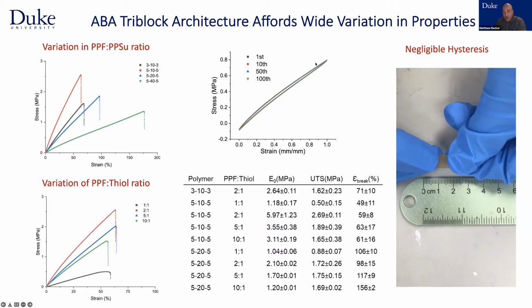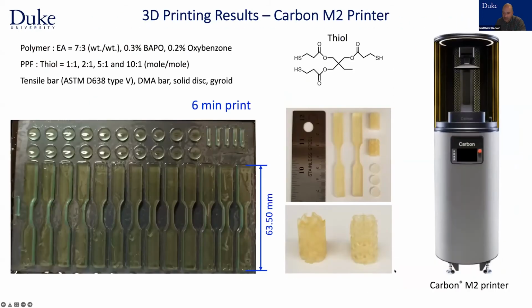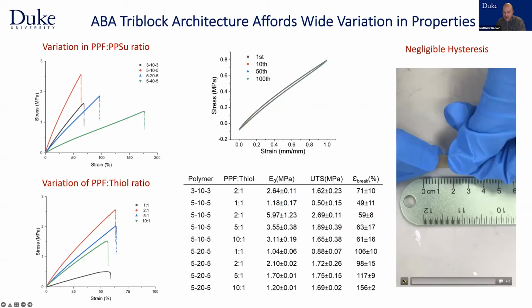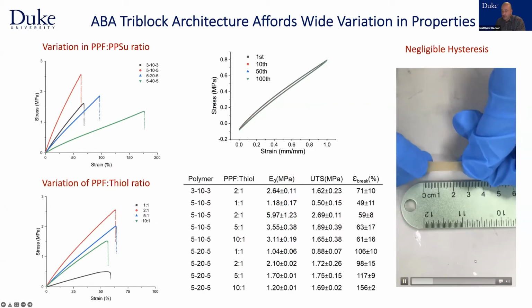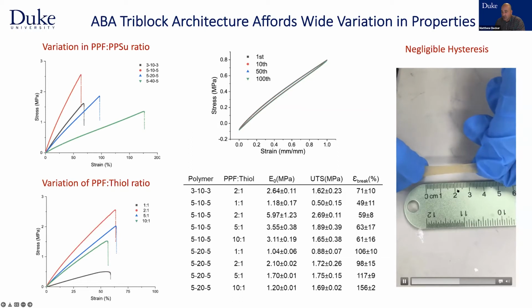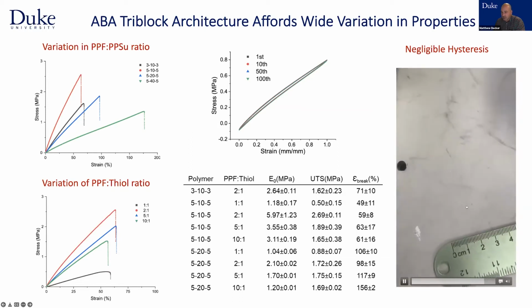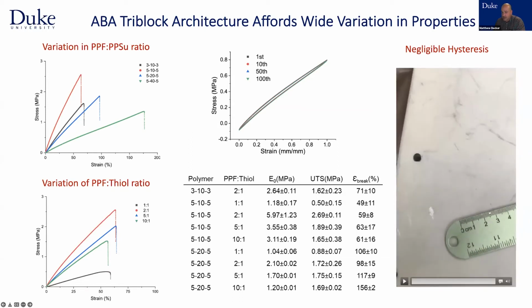And most importantly, there's no hysteresis. And hysteresis is something that's related to fatigue. And what this cyclic test tells you out to 100% strain is that if you strain this repeatedly over time, you'll have the same elasticity. And just to convince you that this can actually be stretched nicely, here's a short video where I've got a graduate student stretching one of our printed structures designed for rib fracture. And you can see that you can get 300 or 400% strain before it breaks. And it's actually quite tough.